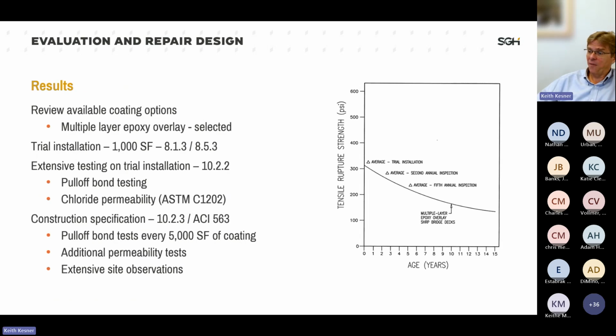As I said, we eventually decided upon applying a multi-layer epoxy overlay. It's bridge deck technology. We did a trial installation. We did a lot of pull bond testing during construction, and we did some more chloride permeability testing to make sure it was working. These are some of the initial results on the right. You can see some of our initial test results that we had, and it was consistent.